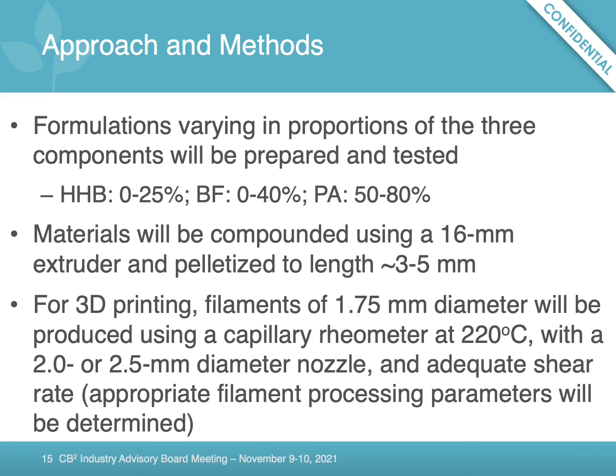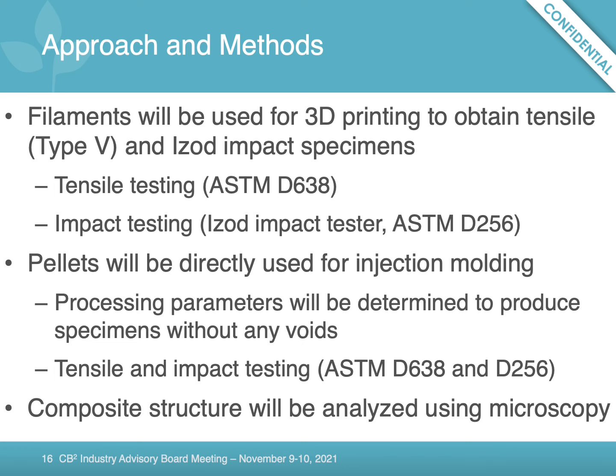And then the materials will be compounded using a 16 millimeter extruder and pelletized to a length of 3 to 5 millimeters. For producing filaments, we'll use a capillary rheometer at 220 degrees centigrade, and the filaments that are 1.75 millimeters in diameter will be produced. Then using these filaments, we'll produce 3D printed tensile and impact specimens, and they'll be tested as shown here using the guidelines outlined in the ASTM standards.